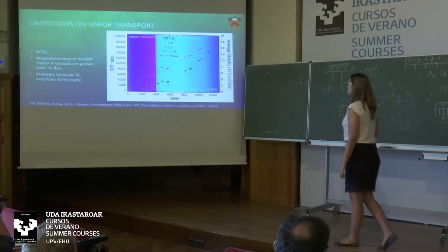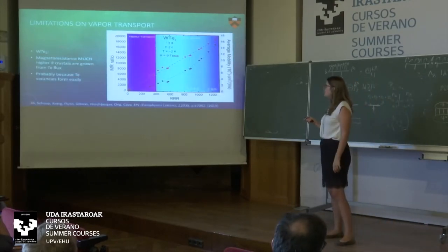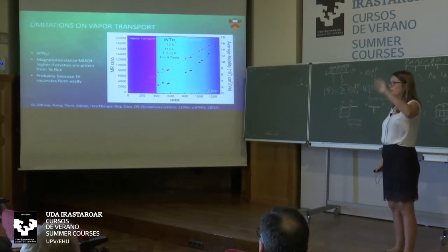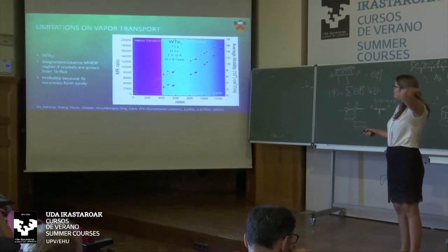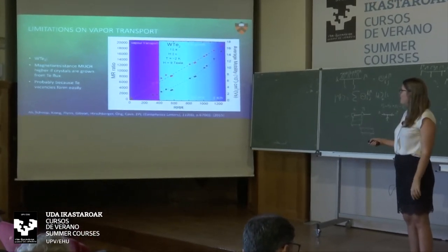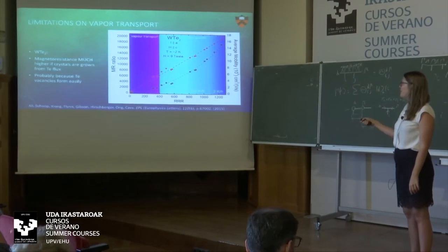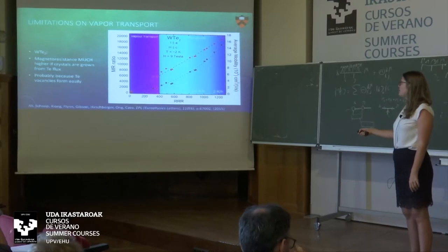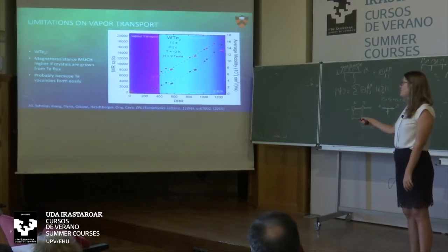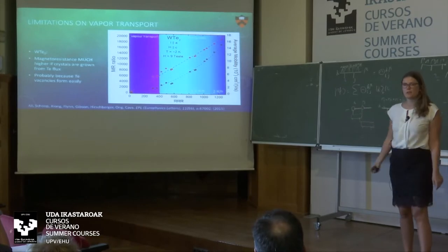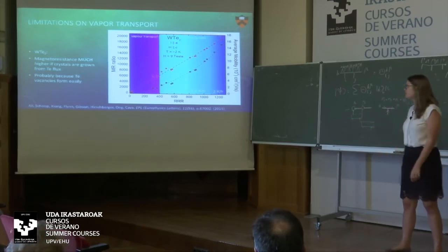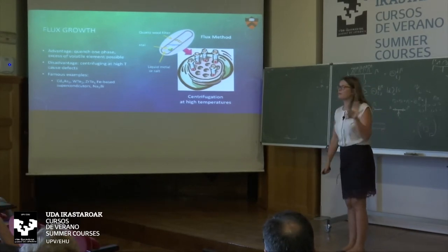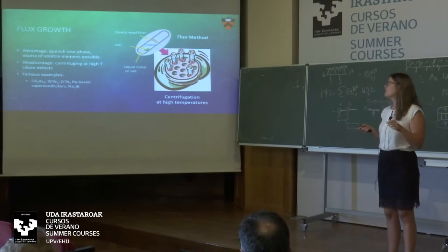Tungsten ditelluride is another example — the first type-II Weyl semimetal showing really high magnetoresistance. Plotting the residual resistance ratio versus MR ratio or mobility, the crystals grown with vapor transport are on the lower end while the flux-grown ones are much more superior in quality. So why? Flux growth is actually the most fun method to do. How it works: you have a quartz tube vessel and put in solid stuff which becomes liquid at really high temperature — a solvent which is a liquid metal or liquid salt.